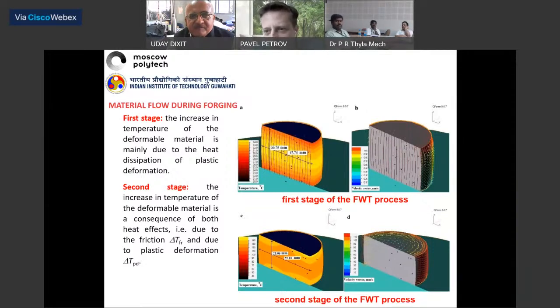Within our project, we looked at the investigation of material structure. In forging with torsion, the specific feature of this process is that the major influence on the plastic deformation is connected to the shear deformation. And the shear deformation in this case is equivalent to severe plastic deformation. So during forging with torsion, it is possible to achieve a very high level of material deformation. As a result, the microstructure changes many times during the rotation of the parts of the workpiece.